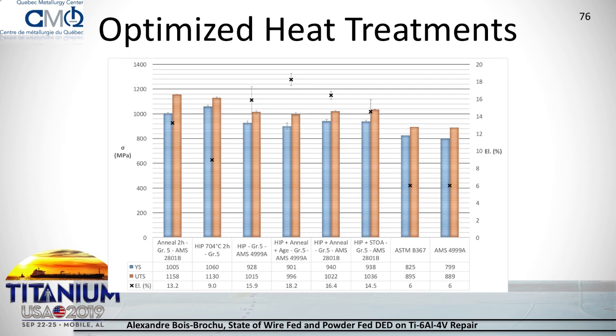And as you can see, HIP plus STOA provides high strength, but HIP plus STOA is quite a complex heat treatment. So you do your HIP, then you do your solution treatment, most of the time in an air furnace because you need to quench in water afterward. And then you do an overage, so you have alpha case formation, and it's much more complex.